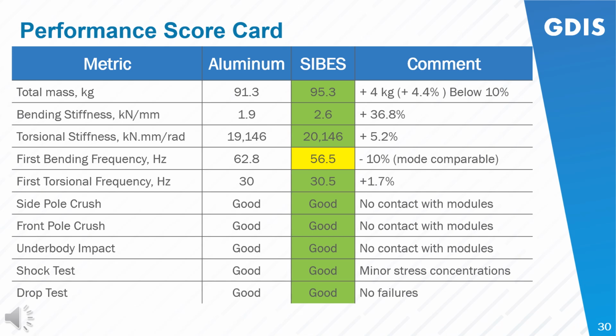We did work hard on optimizing the gauges and the grade and the geometry of the sections to make sure that at least from a spatial perspective it really fits, and then optimizing the grade distribution to make sure that it actually meets all the required nonlinear load cases. But from a refinement perspective, we do expect that with further refinement, especially with a rebalance between the concept of the battery enclosure and the underbody itself, these numbers could improve way farther.